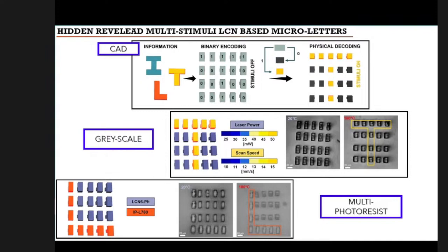In this kind of work, I choose the binary encoding. So when the stimuli is off, you are not able to recognize the letter. Once I switch on the stimuli, thanks to the contraction of the different blocks composing the array, you are able to reveal the letter. As first, I started with a grayscale approach, which means that I change for one step of lithographic technique the contraction and the parameters for all the blocks. And in this case, I was able to obtain different contraction from the same material. And at 180 degrees, you can obtain and reveal the letter T, as you can see.